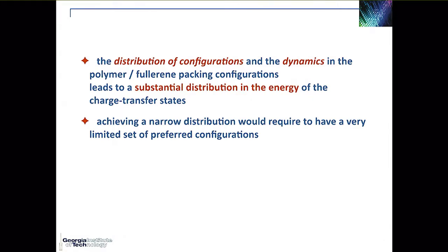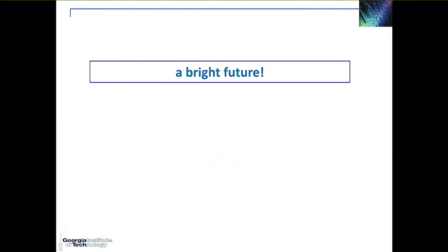And the conclusion that you can make is that achieving a narrow distribution really requires a very limited set of preferred configurations, which is, I think, something that Barry is looking into very much. But the point is, this is maybe the reason why we need to switch to non-fullerene acceptors, not only because with non-fullerene acceptors you can get a much larger absorption within the acceptor component of the cell, but also because they might actually lock in much more strongly preferred configurations of the donor-acceptor complexes. And so that's the reason why I think that there is really a bright future in front of us.